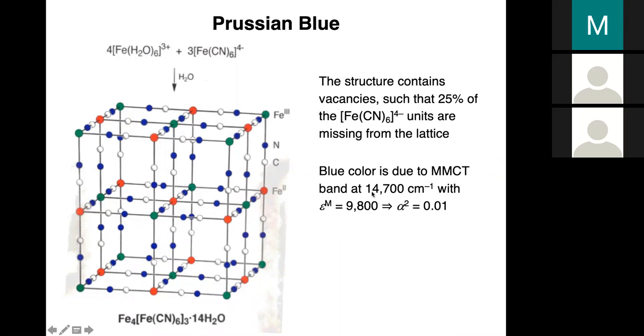And the intensity is associated with the degree of mixing. An important point, beyond what we're going to do here, is that from the extinction coefficient for this MMCT band, you can extract a measure of that mixing parameter alpha. So here, from that band intensity, we get an alpha squared of about 0.01. Right? But this is quite a lot of intensity, and it's giving rise to that really brilliant blue color. Of course, iron 3 complexes with this ligand field are very weakly colored and probably yellow. Ferrocyanide is colorless, with a large band gap.